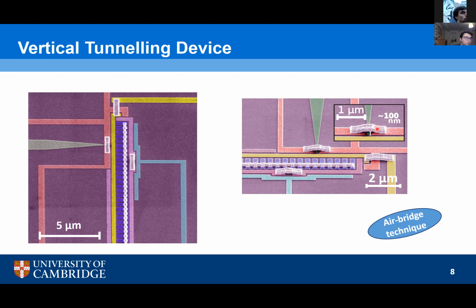And we've been able to fabricate in different devices up to 6,000 bridges in the same chip with all of them connected. And it's a really nice thing to do because before we had this, we had to come up with very creative geometries of getting this tunneling right and getting the wires around each other. Now we don't need that because we can just go over the gates instead of going around. And it also allows us to have more gates. So it allows us to introduce this B gate here.